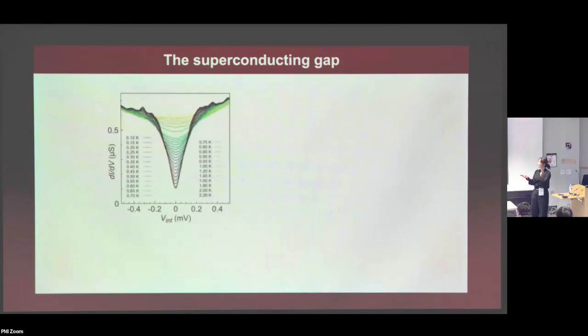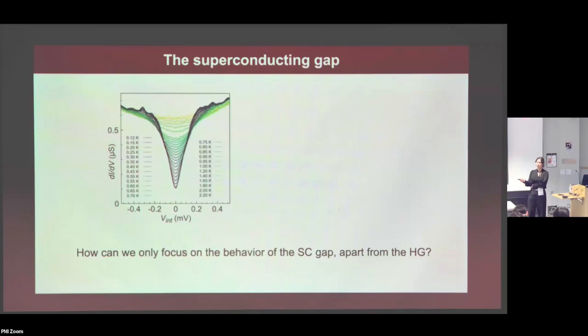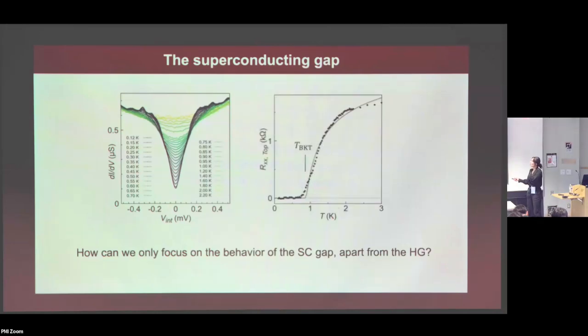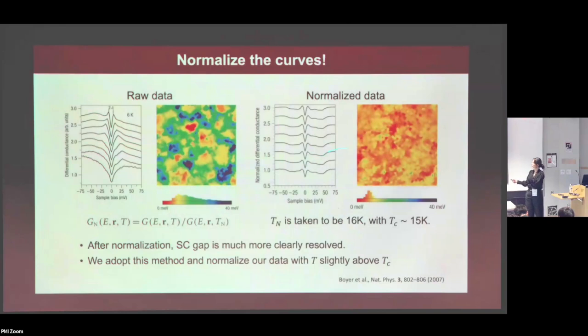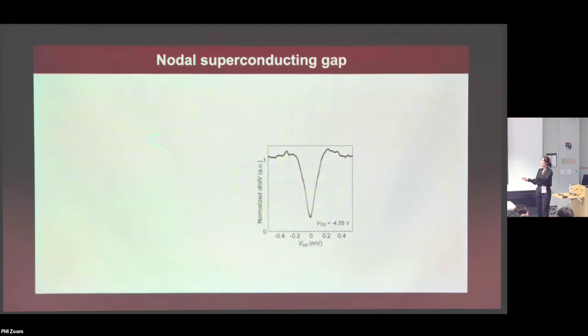So then, what are we going to do? We want to study the superconducting gap, but we also just learned that this curve contains two different things altogether. So how are we going to isolate only the superconducting gap, apart from this coexisting high energy gap? We can take advantage of the normal state curve and learn from the cuprate community to normalize the curves with the curve that's right above the TC, so that you normalize out whatever the higher gap contributions are and are left with only the superconducting contribution to the tunneling curve.